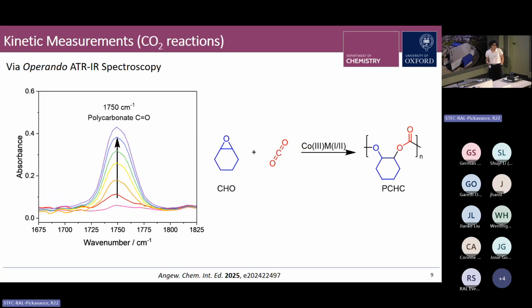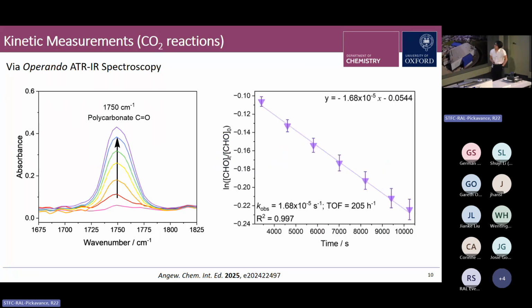The procedure for CO2 is very similar, so we can monitor the increase in polycarbonate concentration by the increase in absorbance of the peak at 1750 wavenumbers. We then calibrate these absorbance time data to concentration time data, and in this case, we're looking at the concentration of the epoxide. So the reaction is first order with respect to the epoxide, CHO, which means the semi-logarithmic plot versus time is linear, and then our observed rate coefficient comes from the modulus of the gradient.